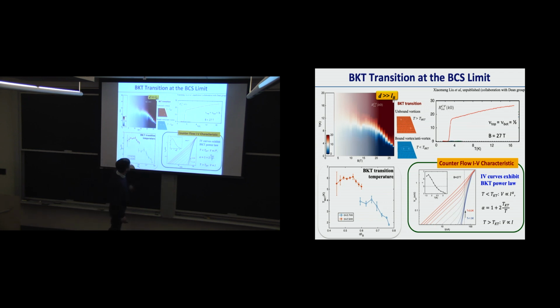You can start to see that these BKT transitions actually nicely align with what happens with the magnetic field direction. We don't have the full understanding of why this type of behavior is happening, but nevertheless, this shows that this type of IV characteristic in counterflow geometry gives BKT transition temperatures with nice scaling, strongly suggesting that this can be almost kind of like the BCS type of transition we have.